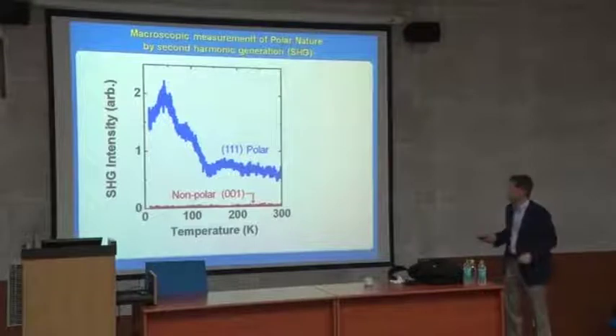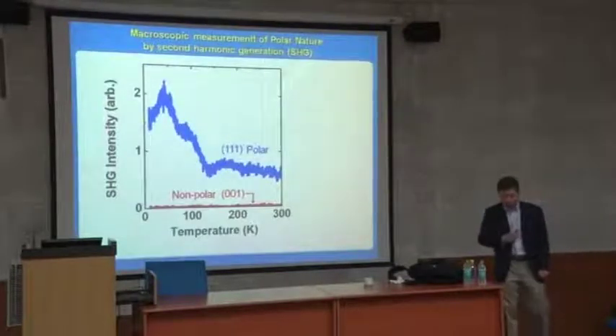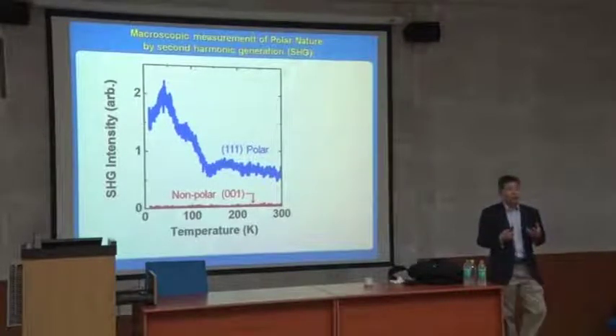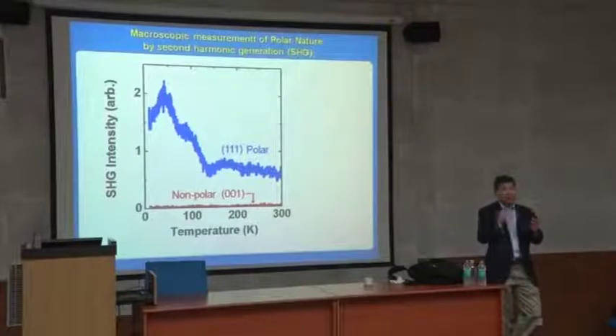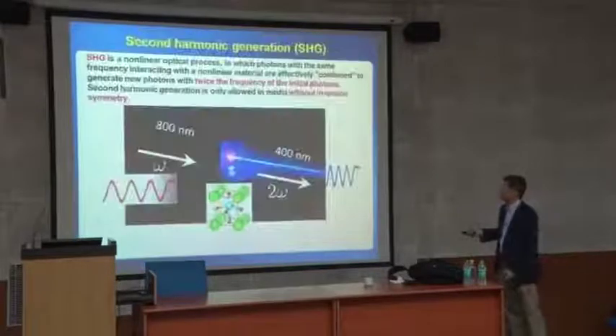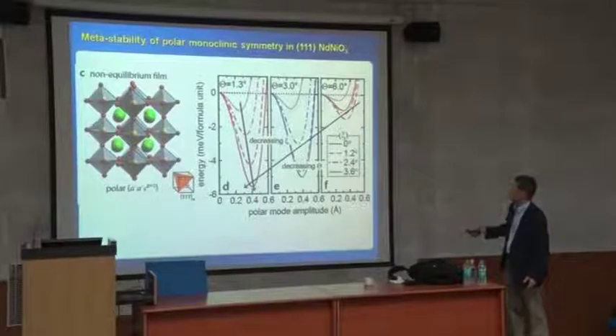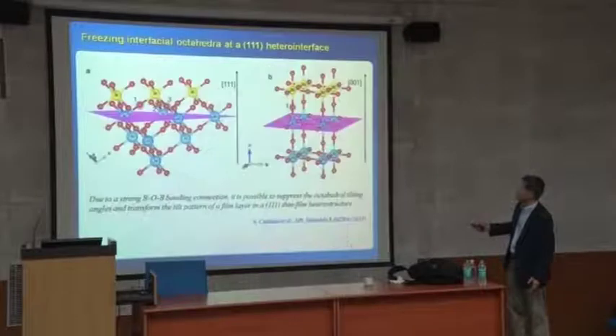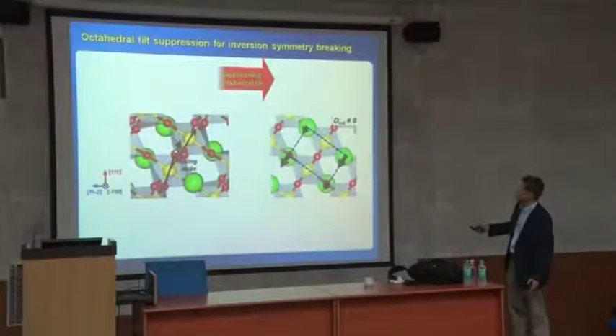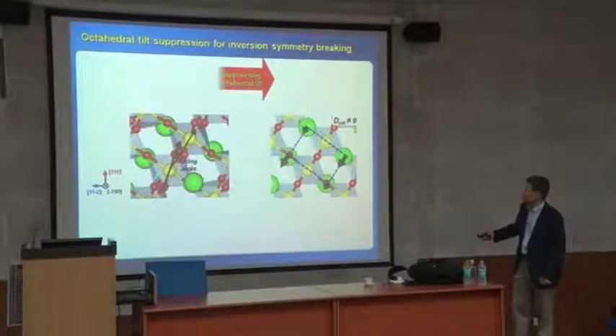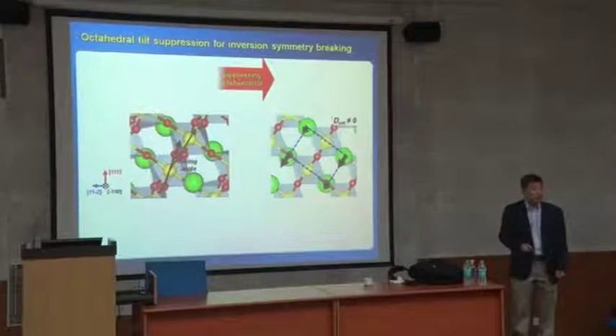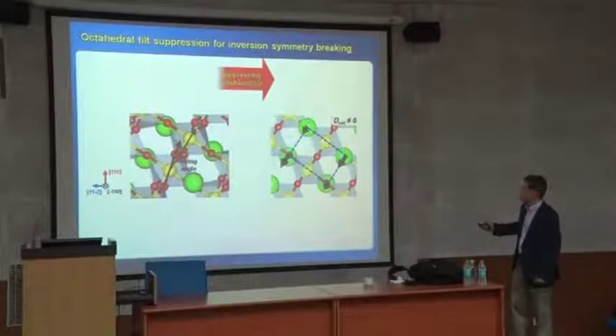rotation. Okay? This is one way to do it, but the second question, which we talked about in the beginning, is whether the mechanism of suppressing the tilting really does something. Because your calculation shows your suppression angle. You see that suppression angle here? This suppressed angle is a smaller angle, gaining energy, so more stable. At the same time, the schematic diagram here shows you suppressing this, stretching this tilting angle. So I want to really measure this angle, whether it is really suppressed or not. And I also want to know whether this really happened, whether the atomic position here is really displaced like this.